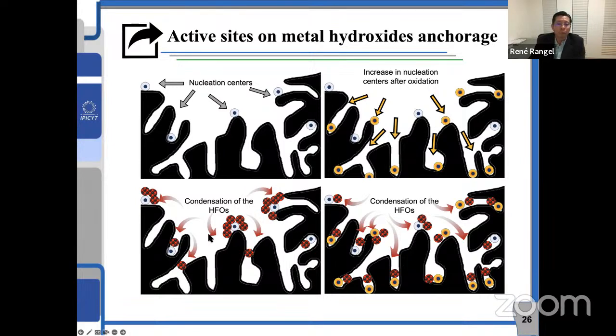Okay, so we can anchor different metal oxides. In this case, you can see in red dots. Well, one of our ideas, okay, I want to increase more the concentration of metal oxide, aiming at a higher sorption capacity of arsenic. So we said, okay, what if we oxidize the material? We will increase the amount of nucleation centers. In other words, we will increase the concentration of the oxygen-containing groups, and then we will have a higher concentration of metal oxides, and with that, a higher sorption capacity.